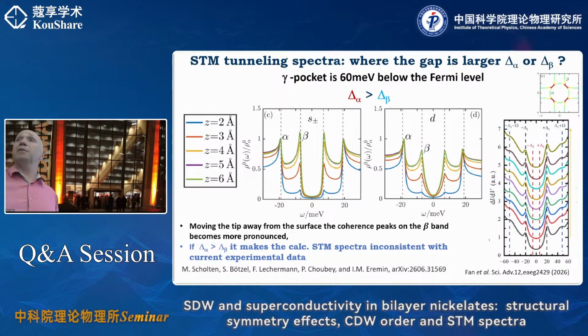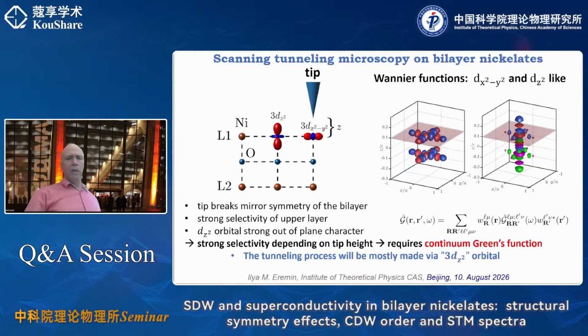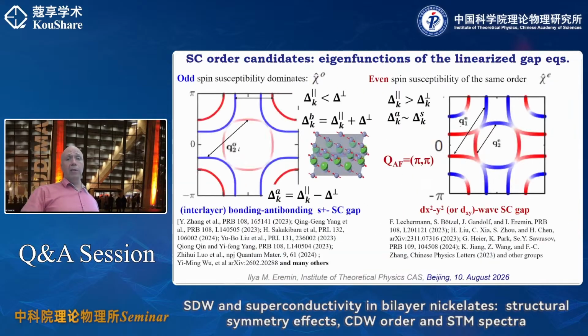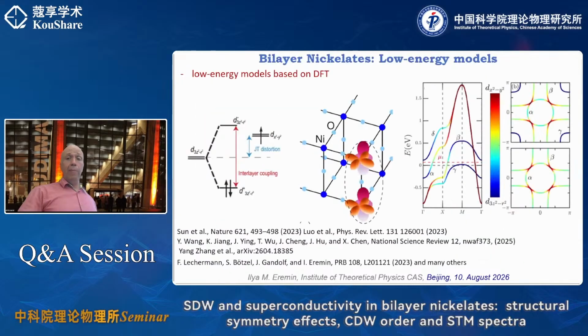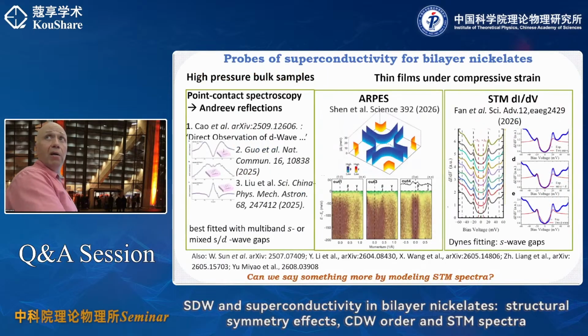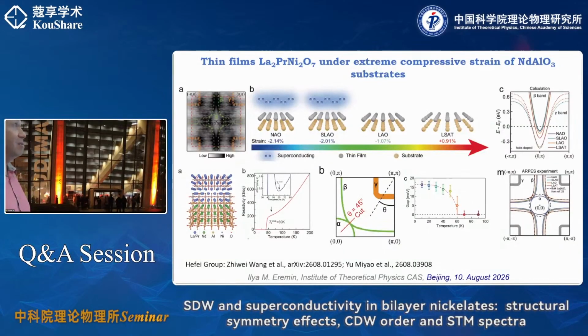But we have ARPES. Of course, ARPES is unambiguous. So what we know now is that they see this gap, which means at least certainly that there is no D wave. And it appeared last week. Previously that was a statement by the SUSTech group, the only group which made this statement. Now they see it in this other substrate, and they see that the gap is maximum here, with this value. Actually, the ARPES was done by the same group in Hefei.